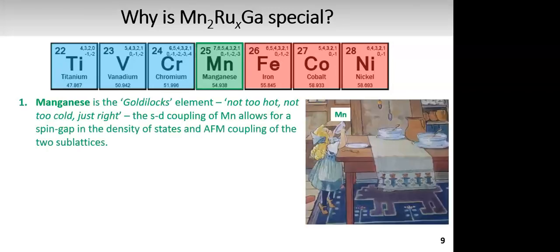So first, starting with manganese, it is like a Goldilocks element. Here we have an illustration of Goldilocks drinking the porridge that is not too hot and not too cold. And this refers to the sd coupling of manganese, which allows for the spin gap in the density of states and therefore high spin polarization. And it also is not too strong or too weak for antiferromagnetic coupling of the two sublattices.